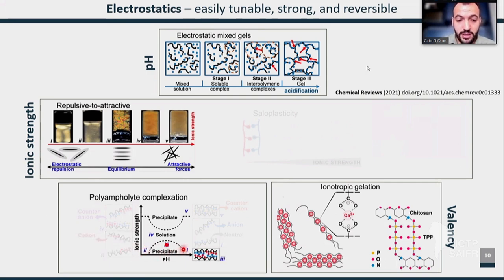As we go to intermediate pH, meaning that we are above the pKa of the anionic block and below the pKa of the cationic block, we can have both charges active, right? So one chain having both charges, and they can easily complex. This is what we call the precipitation. So we are in this region of the pseudo phase diagram, right? So let's keep this pH that can trigger the complexation and so precipitation, and go up in ionic strength. As we put salt, or, you know, small electrolytes, they are responsible for screening the electrical double layer.